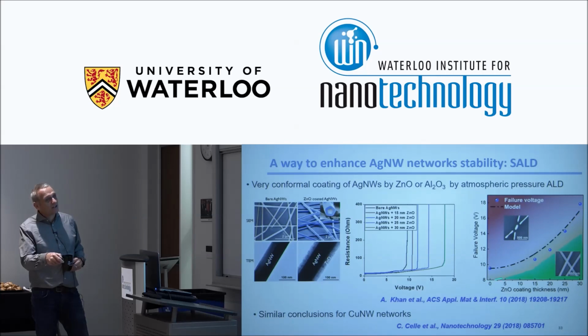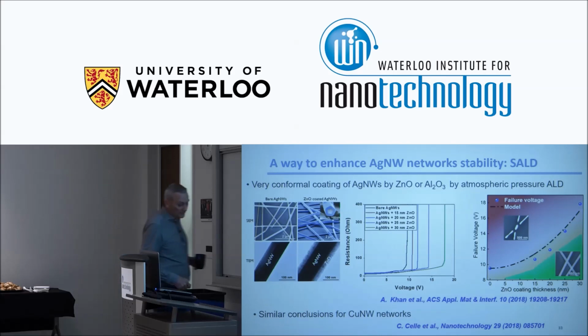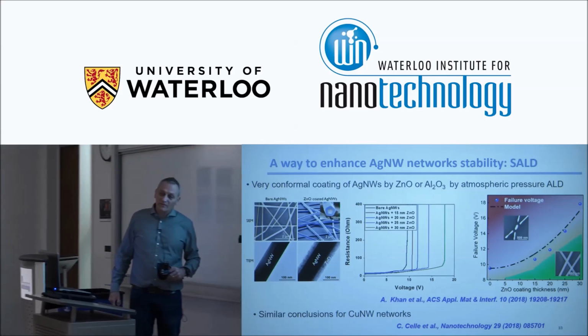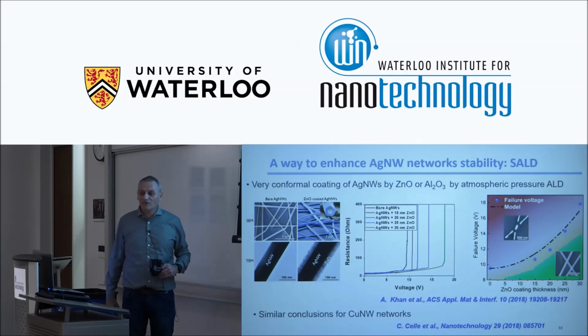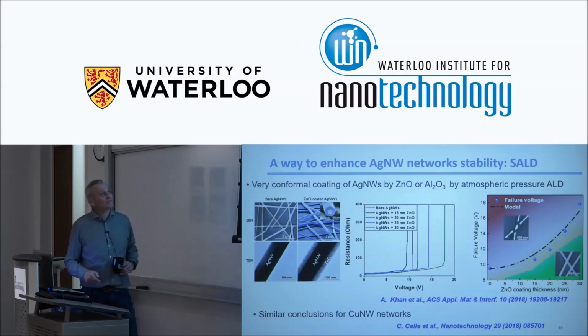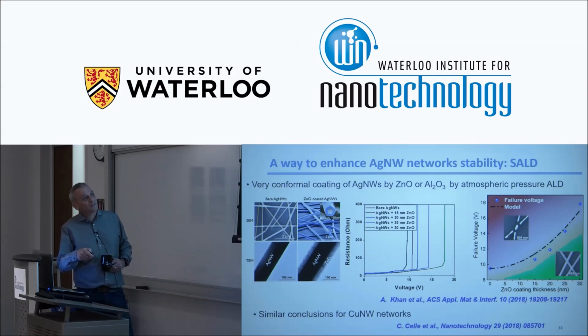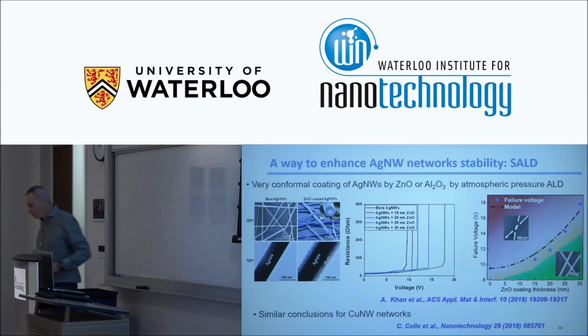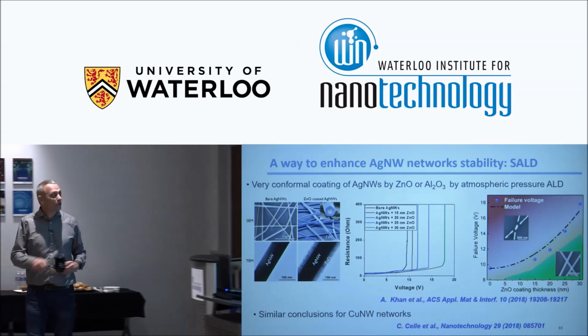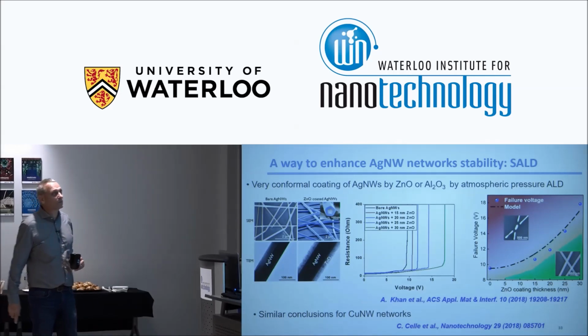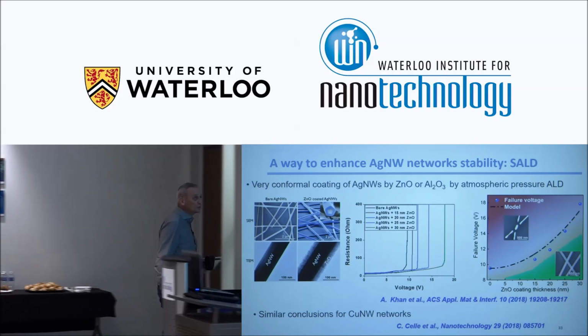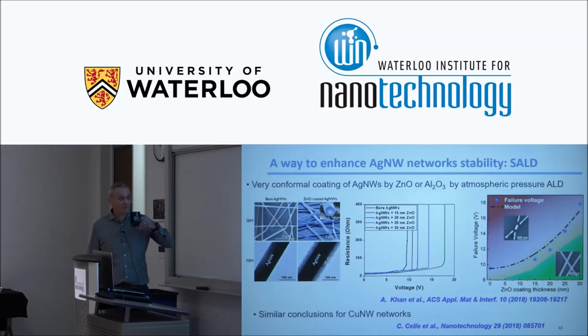And if we plot the failure voltage versus the zinc oxide coating thickness, the blue points correspond to the experimental observation, and we have derived a very simple physical model which comes from silver atomic diffusion models. We have this fitting curve here, which fits well with the experimental data. Here we are on the safe side, and here we are on the failure side. Okay, so we have published that this year in ACS Applied Materials & Interfaces, but we also work with Jean-Pierre Simonato's team on copper nanowires, and for sure we can get about the same result as well. So that's a nice way to coat the silver nanowires and to make them much more stable.